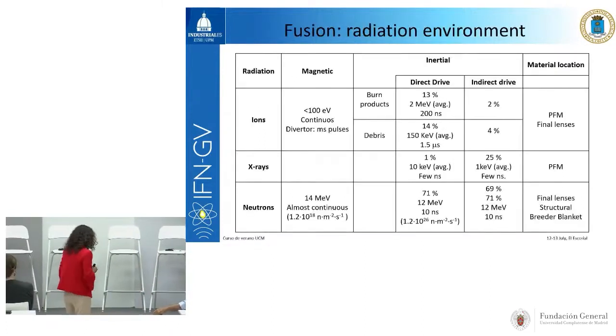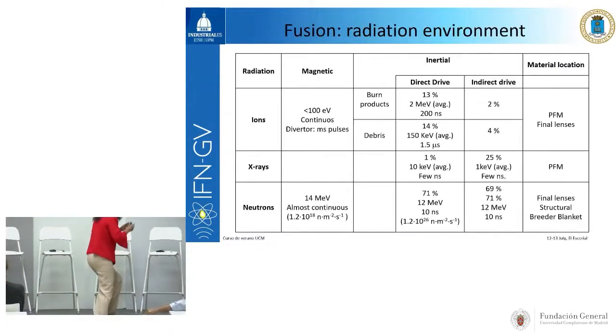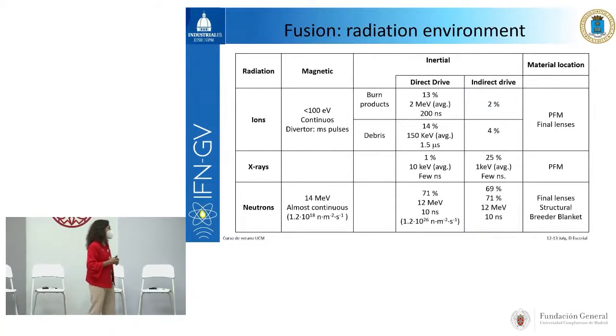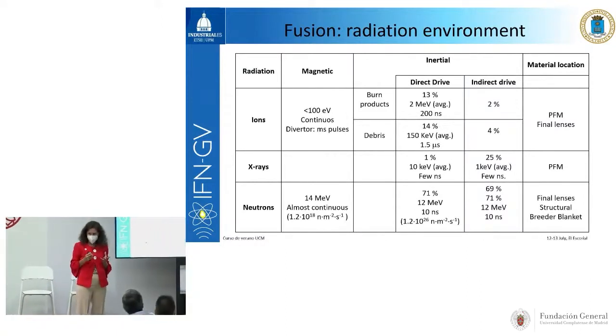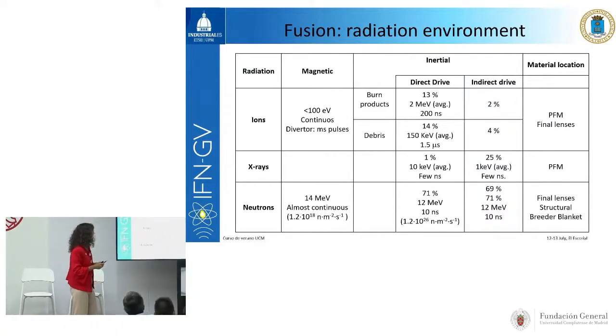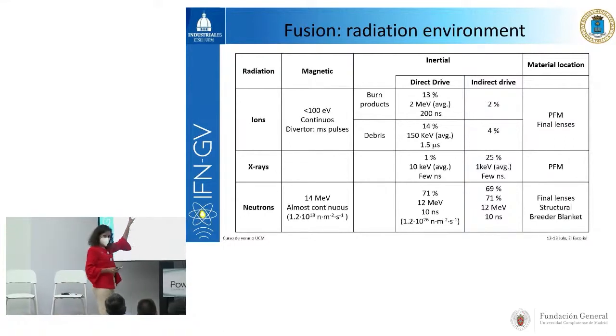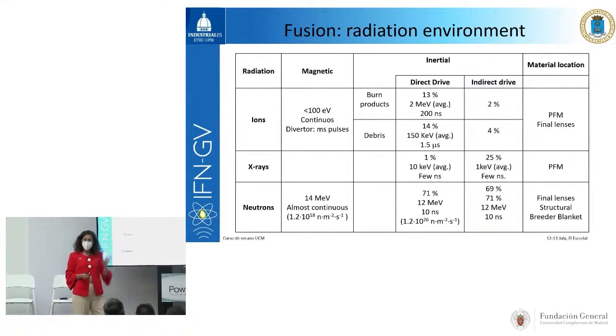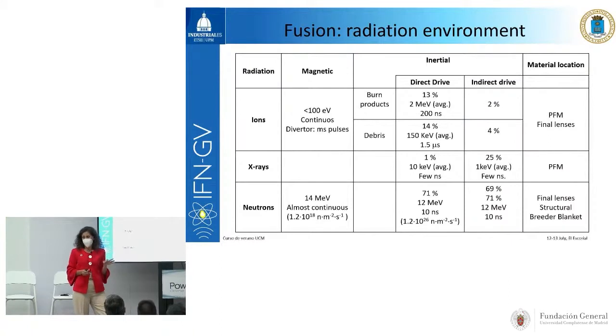So basically, this is a table to summarize the most important threats that the material has to withstand when located in the reactor. So here we identify ions, okay? Ions are going to be the main threat basically for plasma-facing material, because the penetration range for neutrons is very long, so the first wall of the material basically is not going to see the neutrons, but ions. And then we have to make a difference.